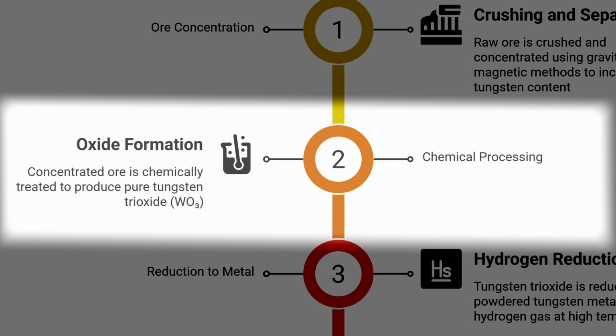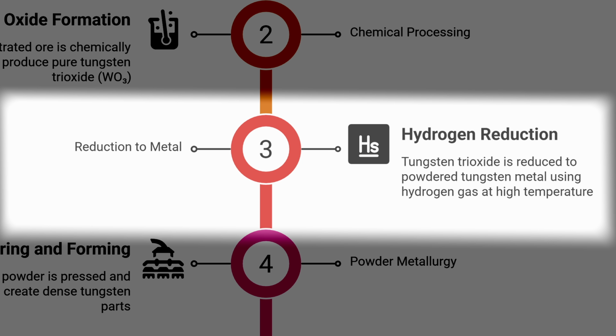The concentrated ore is then chemically processed to convert into pure tungsten oxide. One common method is to digest the concentrate in an alkaline solution. For example, scheelite can be decomposed by boiling it in sodium hydroxide solution, which dissolves the tungsten into a sodium tungstate solution. Wolframite concentrate might be fused with sodium carbonate. In either case, the goal is to get a soluble tungstate compound. The solution is then acidified, causing tungstic acid or hydrated tungsten oxide to precipitate out. This precipitate is filtered and roasted to yield pure tungsten trioxide, a fine yellow powder.